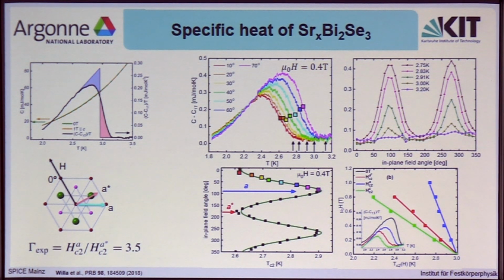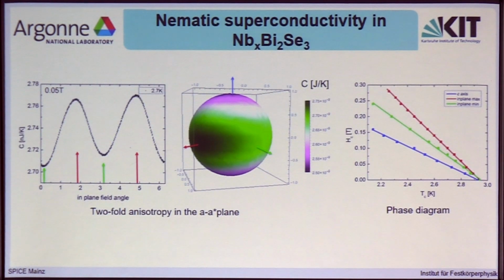Now we've done similar measurements for niobium-doped bismuth selenide. Here, since the specific heat jump is much larger than in the strontium-doped compound, we can already start to see this twofold anisotropy by taking a very small field of about 50 millitesla and just monitor the specific heat at a constant temperature at about the superconducting transition, and you clearly see this twofold anisotropy when the field rotates in the plane. We've actually even extracted the full three-dimensional plot of the specific heat, also for a field of 50 millitesla rotating in 3 dimensions in our triple-axis cryostat.